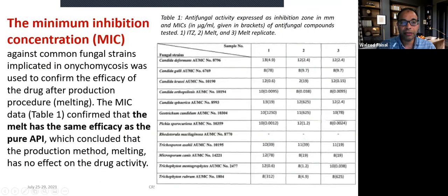When we use the minimum inhibitory concentration, again, there are different fungi and yeast strains which are implicated in onychomycosis. The data in the table confirms that the melt has the same efficacy as the API, and also the melt after 3 months is still giving the same efficacy.